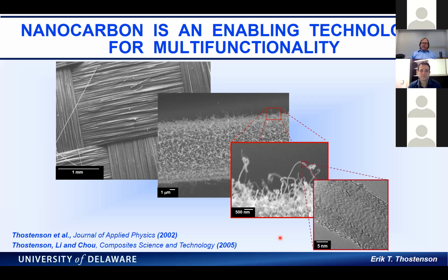But what really grew out of that is that I did a lot of work in this area, and then we were looked at electrical properties and thermal properties. I think it really is the multifunctionality aspect. We have utilized electrophoretic deposition, and we see nice increases in the interfacial strength and fracture toughness when we combine them with fibers.